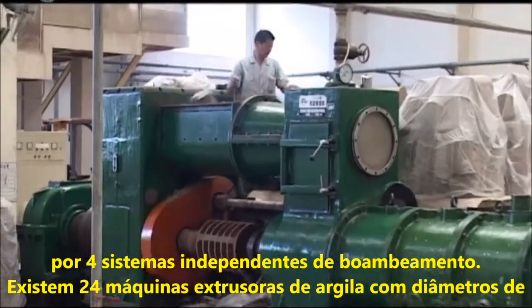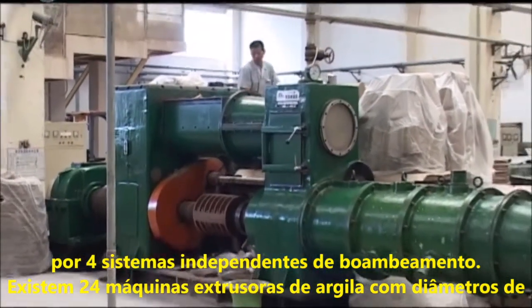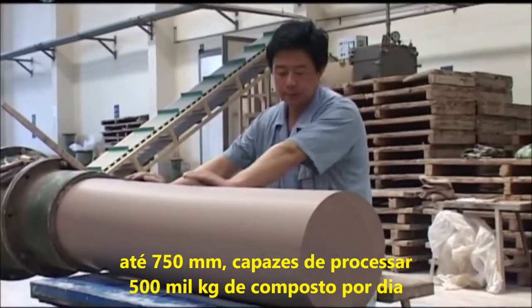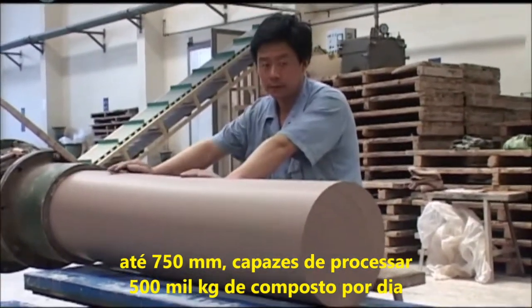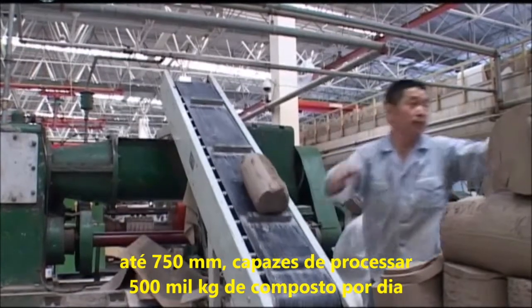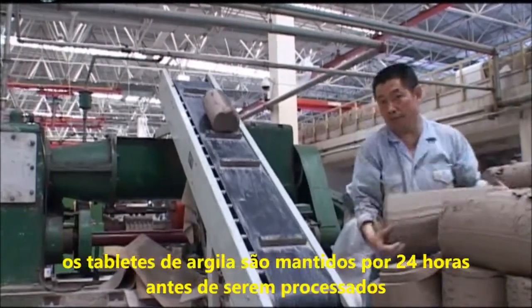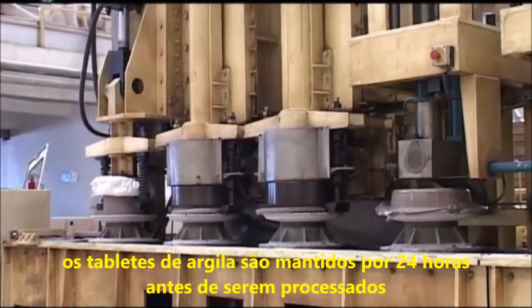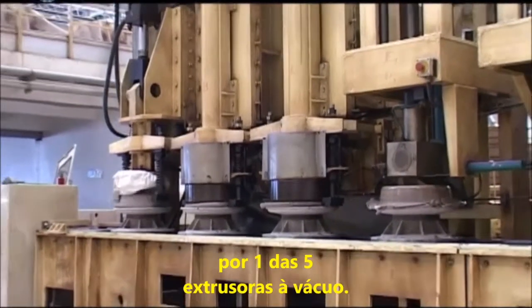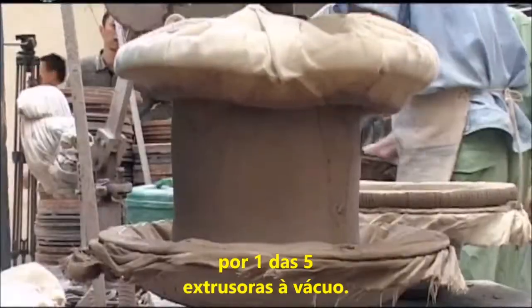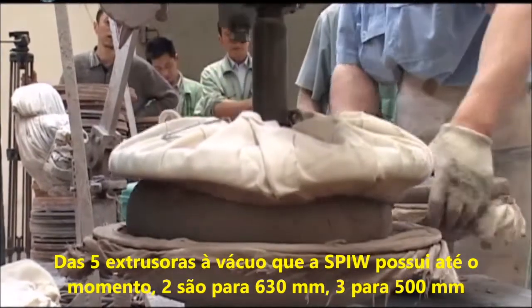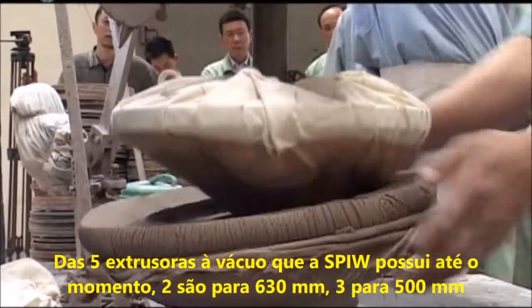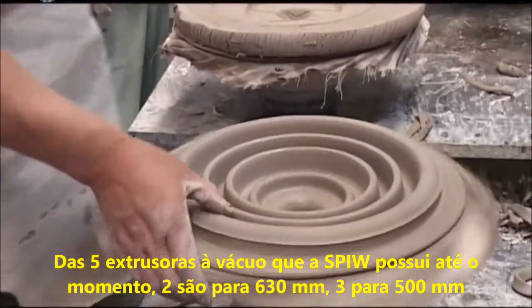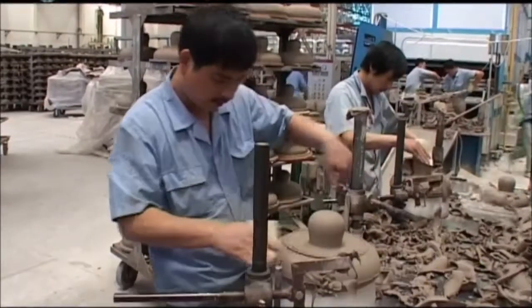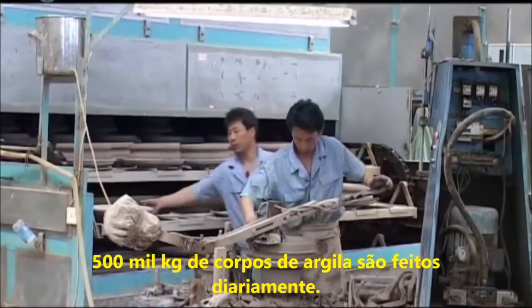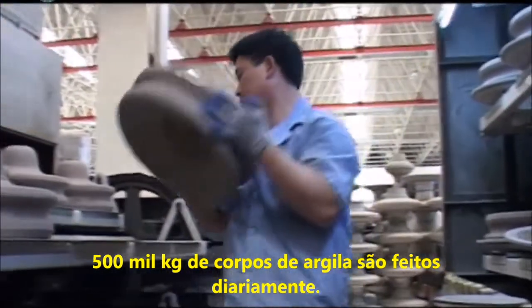There are 24 mud press machines with diameters to 750 millimeters, capable of processing 1,100,000 pounds of compound per day. The clay tablets are held for 24 hours before they are processed through one of the 5 vacuum pug mills. We have 5 vacuum pug mills now, 2 for 630 millimeters, 3 for 500 millimeters. 1,100,000 pounds of mud body are made daily.